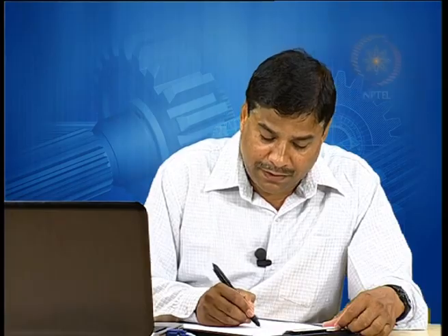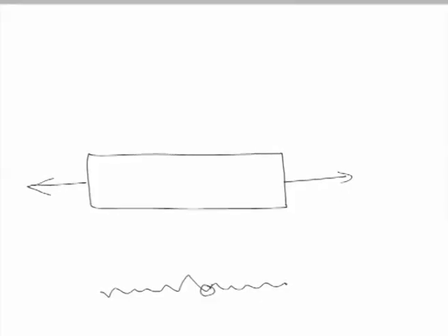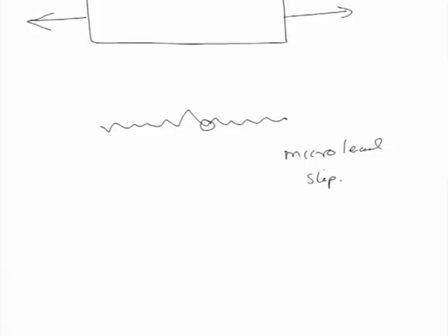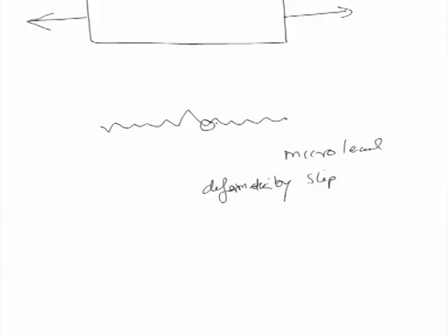So, wherever the deep valleys are present, those areas under the load fluctuation will be showing some minor stress localization, and at these locations, very micro level deformation will be occurring by slip. So, micro level deformation occurring at the surface by slip will be facilitating the development of the crack after a large number of the load cycles.